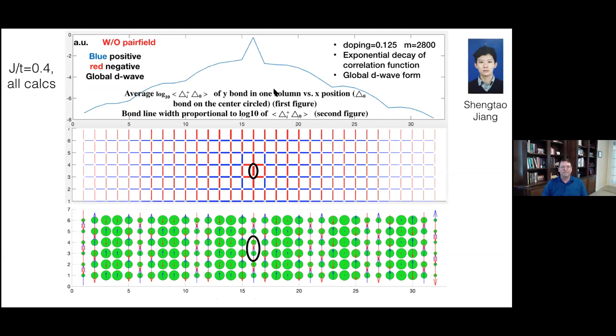And this is a measurement, in this case a pair correlation, where the location of one of the pairs is this bond. Then it's plotted for all the other bonds where we measure the other part of the pair correlation. You can see the D-wave nature of most of this, but it says here, log 10. This is on a log 10 scale.